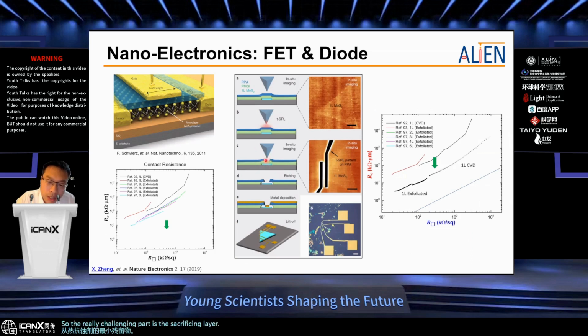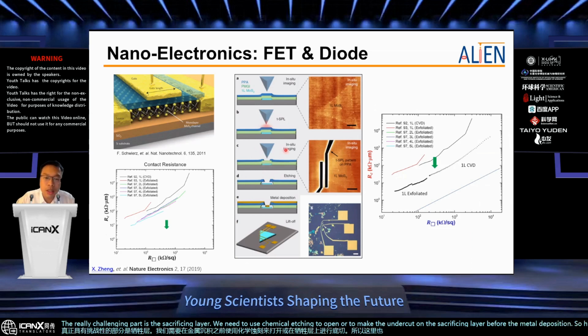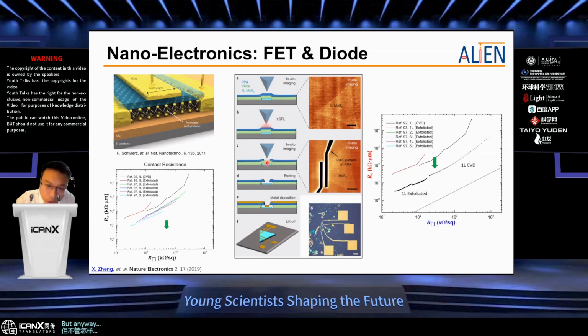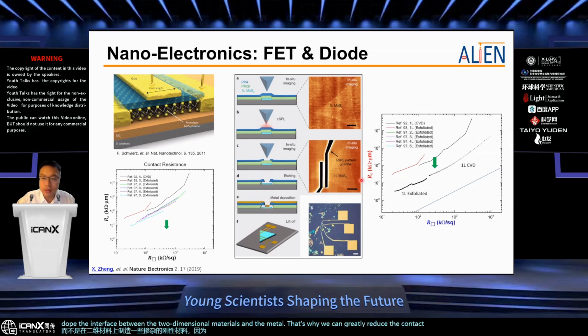We need to use chemical etching to make the undercut on the sacrificing layer before the metal deposition. At that time, it is also corrosive from the chemicals. But anyway, we can try to tune the chemicals here to create some doped region on the two-dimensional materials. Because we can dope the interface between the two-dimensional materials and the metal, we can greatly reduce the contact resistance between these two samples.